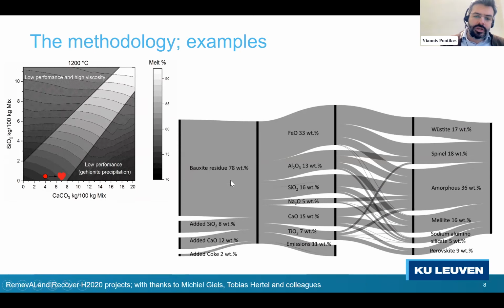So we want the majority to be the residue. And in this case, silica and calcium are just minor components. You still need some carbon because you need to go from iron 3 to iron 2. Now, of course, we're working also with hydrogen, and this carbon can also be biogenic carbon, so it doesn't necessarily contribute to more CO2 emissions. On the right-hand side, you see thermodynamic equilibrium, but depending on the cooling rate and the glass forming ability of your melt, you might have more of this component, which is important: the amorphous fraction.